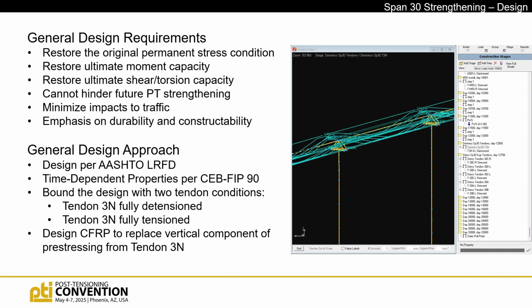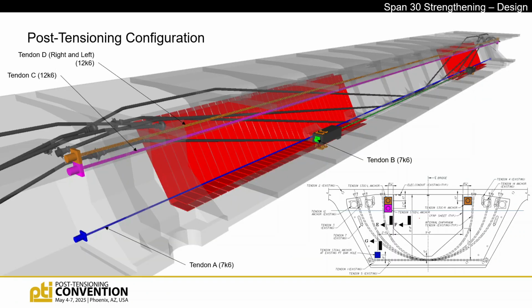And since we didn't have to do the drape tendon for the principal tension, but we did want to restore the ultimate shear capacity, we went with CFRP sheets on the webs, and that's what you see here, the red stripes. And then the rest of the solution here was 5 tendons. You see in the bottom, tendons A and B are 7-strand tendons, and then C and D are 12-strand tendons up high. Now, the damage was on one side of the bridge, so it's an asymmetric solution. One of those top slab tendons, tendon D, is mirrored to the right side of the structure.